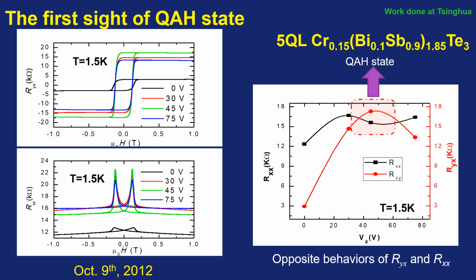If we plot the zero field longitudinal resistance and Hall resistance as a function of the gate voltage, we can see in this sample, different from the previous sample, the Hall resistance goes up. At the same time, the longitudinal resistance goes down. In a ferromagnetic material, the Hall resistance is usually proportional to the longitudinal resistance. But in this sample, the Hall resistance becomes bigger while this becomes smaller, which indicates there is some quantum state in this sample.